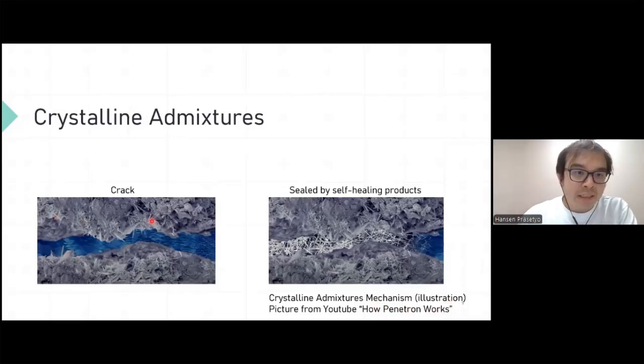So in the cement matrix, when a crack happens, you see water goes in, and then also air, and then it reacts. The crystalline admixtures react with it, and it creates this crystalline formation that seals up the crack. By sealing the cracks, we delay the chloride ingress and hopefully prolong the service life. So we try to prevent chloride from reaching the steel bar.